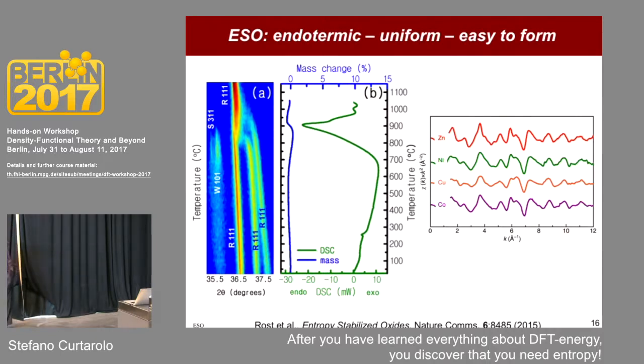And you can also see with differential scanning calorimetry that if you go from low temperature to high temperature, you do the 2 theta as a function of temperature and you plot it. You see that we are not losing mass, and the transformation is exothermic if you go down, and endothermic if you go up. So this has the characteristics of really a melting. This is a melting of 5 components that becomes a homogeneous thing. So this is a new class of systems which we call high entropy oxides, and it was published in Nature Communications 1.5 years ago.